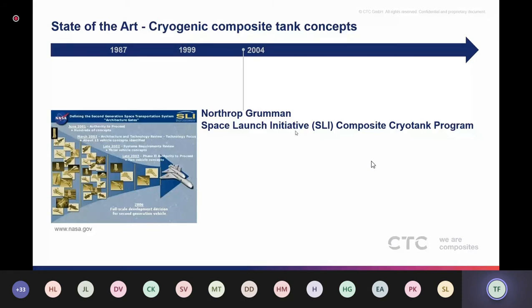Another thing that was done was to introduce an aluminum foil between the inner skin and the honeycomb core as a barrier for hydrogen permeation. And the honeycomb core was subjected to vacuum to suck out any permeating hydrogen. These tanks were successful in testing, where after 40 filling cycles, the tank still maintained its structural integrity.